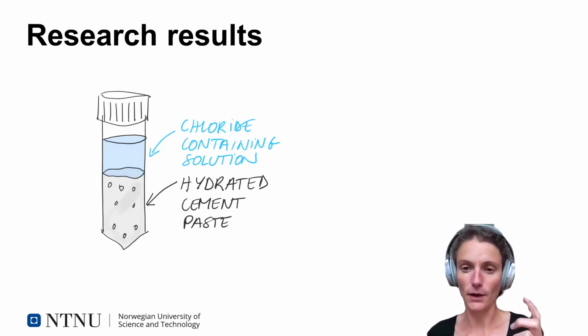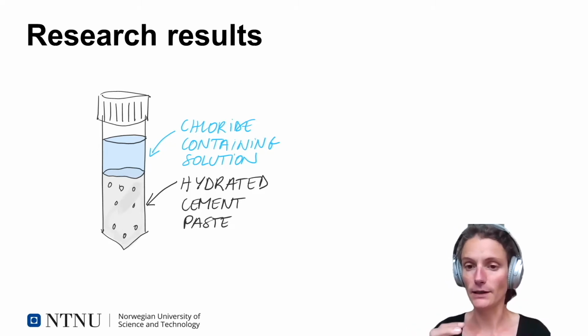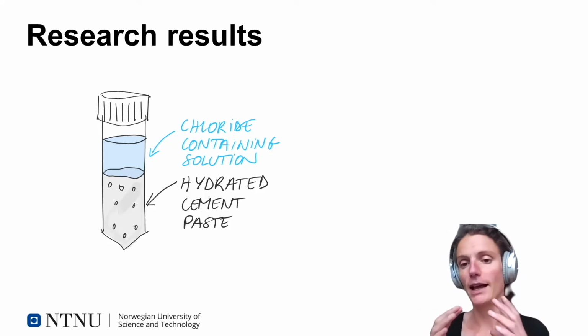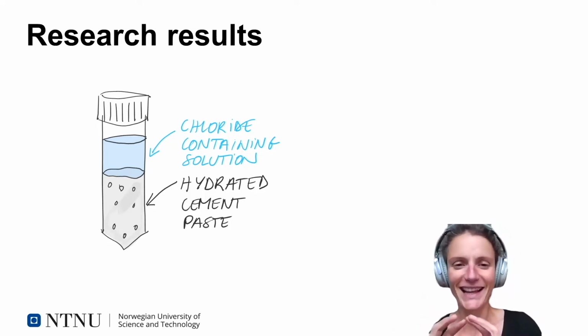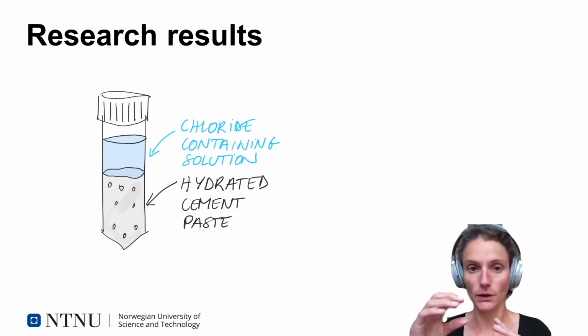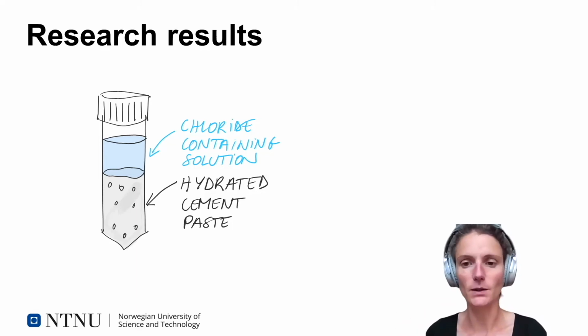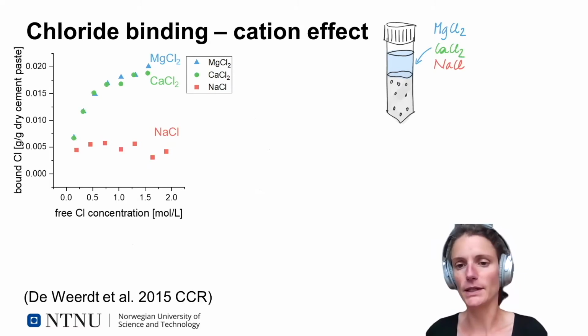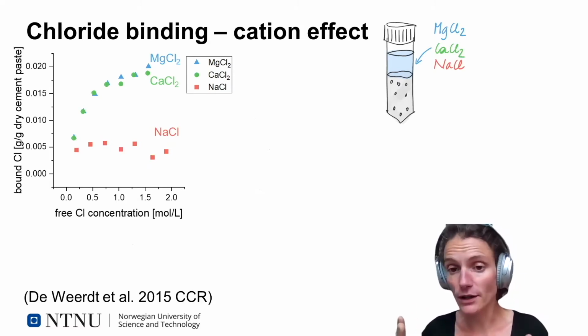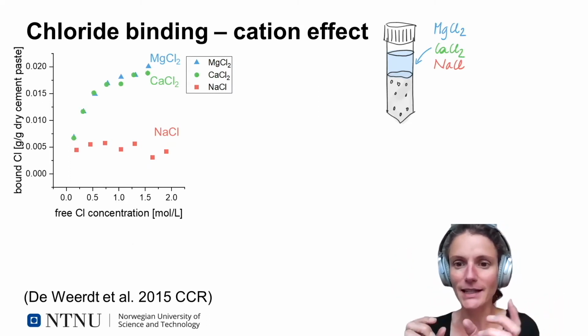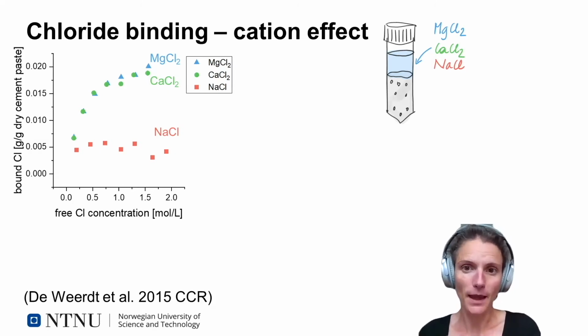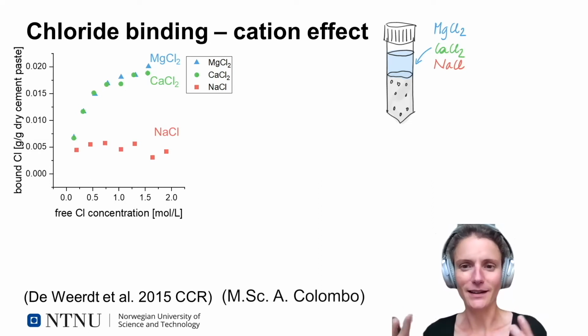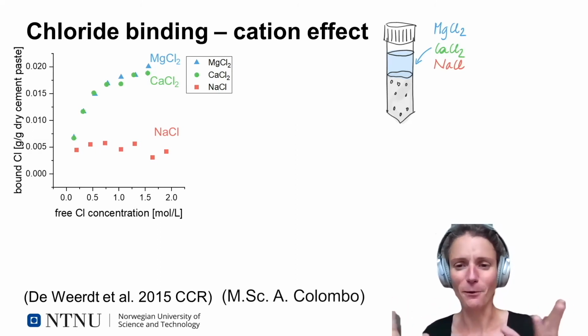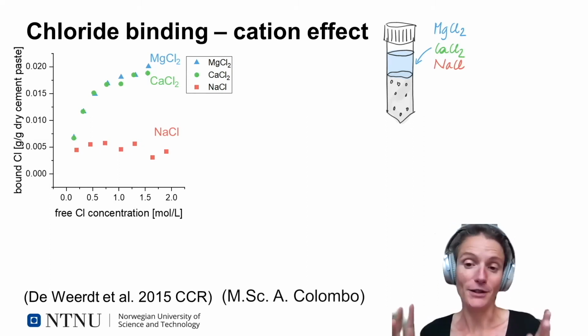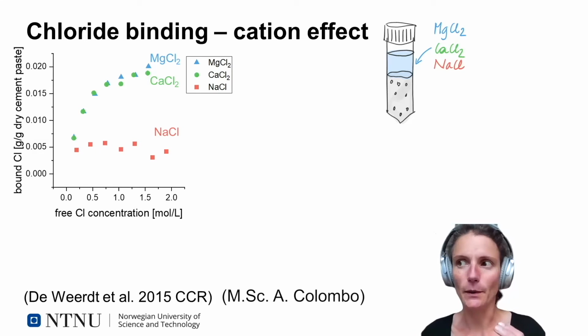And in these tests, we have put hydrated cement paste in contact with chloride-containing solutions in a closed container, and that tends to equilibrate, shaking them sometimes. And then when we've reached equilibrium, we will analyze the pore solution and the solids and try to understand how these two interact. In the first study, we looked into the cation effect. The cation is the positively charged ion which combines with the chloride in the salt. So in this case, this is magnesium, calcium, or sodium. It is known that the cation plays an important role in chloride binding, though the explanations for it vary widely. So in order to understand chloride binding, one typically determines something which is called a binding isotherm.